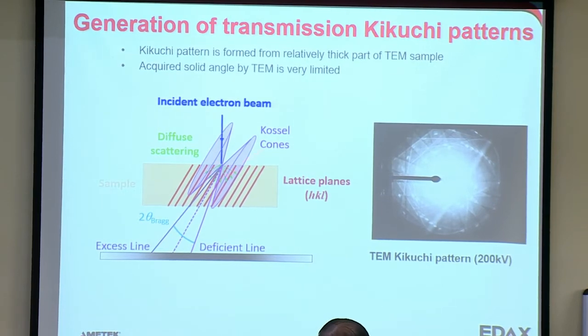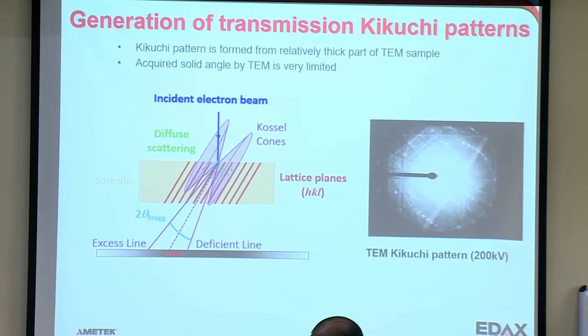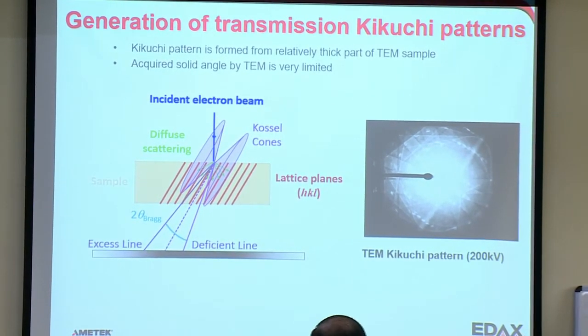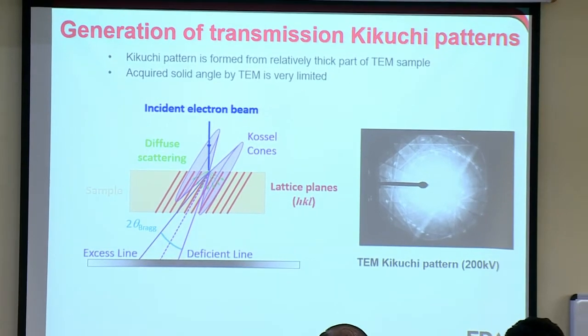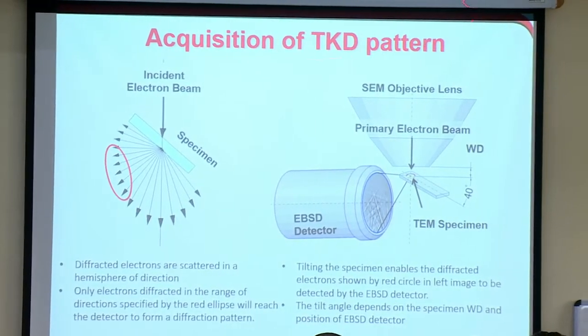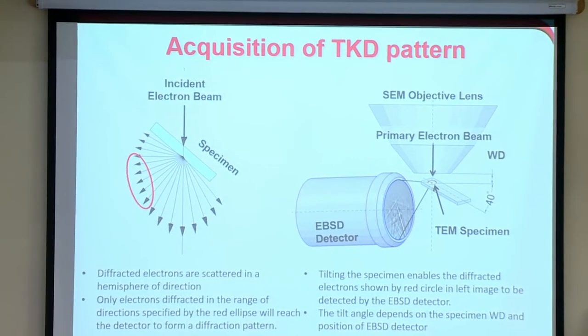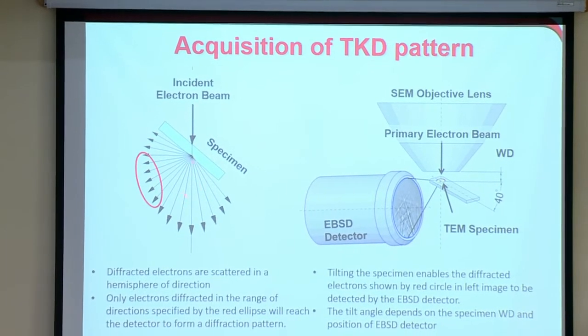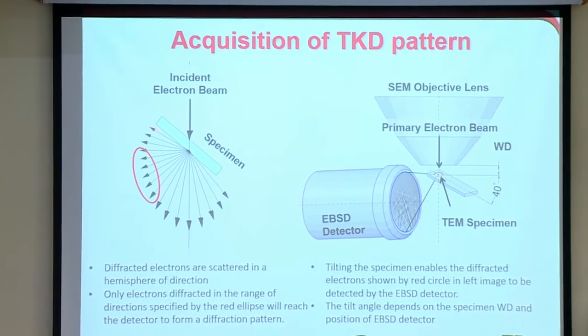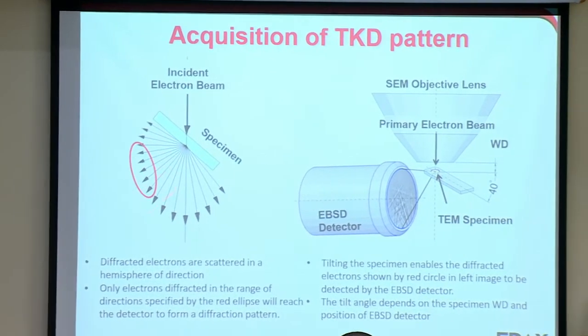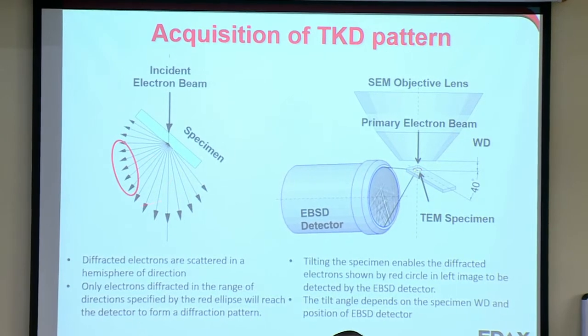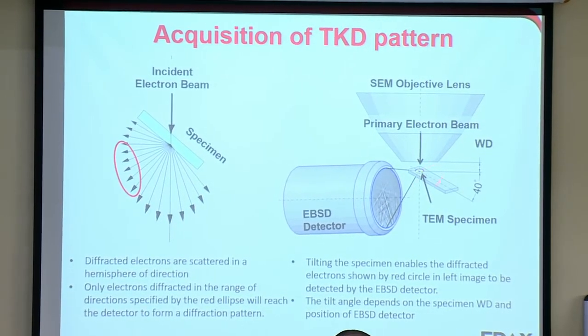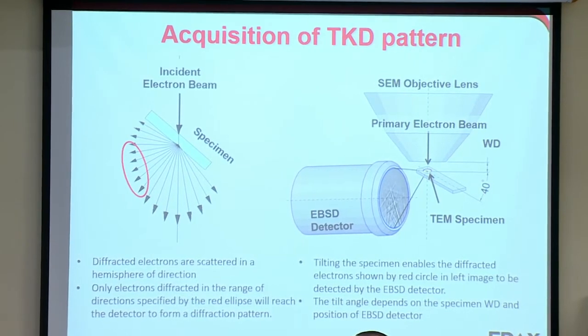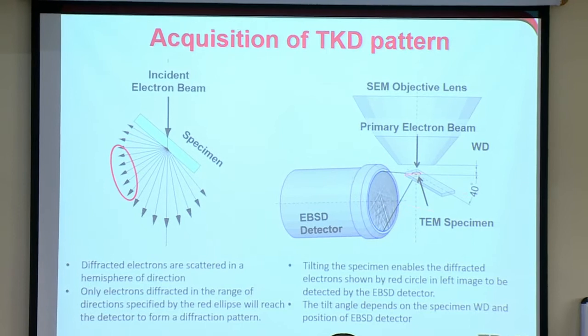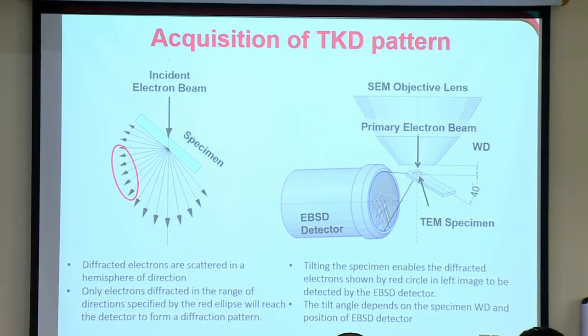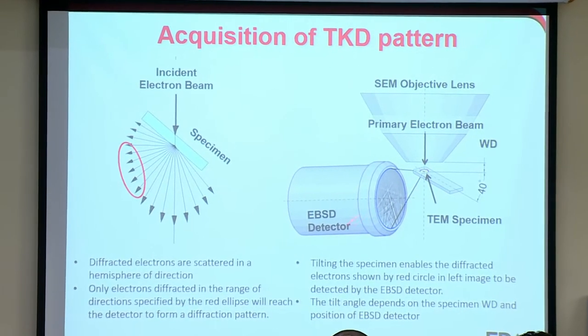You have an electron beam. Those electrons that satisfy Bragg diffraction produce an excess line and a deficient line. And so you get patterns that look like this. This is a TEM Kikuchi diffraction pattern. Now, in a TKD pattern, transmission Kikuchi diffraction in the SEM, you put a transmission electron sample in, put your electron beam in, and now all your diffracted electrons are coming down below the sample. And so we can put it in a lot different orientation than we did with EBSD. So now we just have a small tilt. 40 degrees is actually kind of atypical. It's a lot. And we look at the diffraction pattern that's formed here.